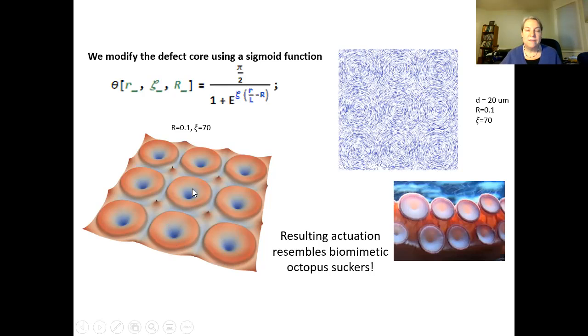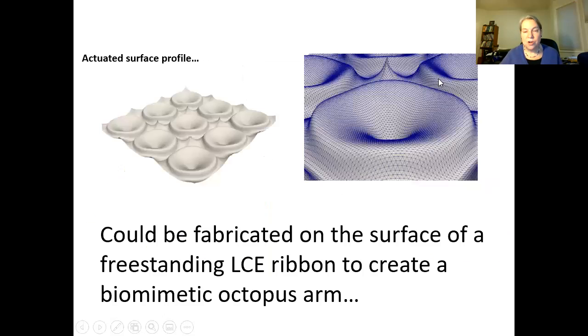So my student, Yusuf Golestani, decided to consider, what if we look at a matrix of defects and use what we've learned from structures of defects in regular liquid crystals, not necessarily polymers, to spread the core of the defect out a little bit. He tried some different parameters. This is an actuation that came from a flat surface. When actuated, it forms these octopus sucker-like shapes. And if you look more closely, you can see how the finite element mesh looks.